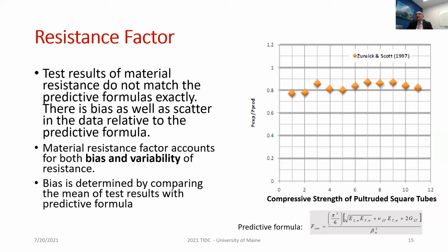What is bias? I present to you the compressive strength of pultruded square tubes, and you will see that using the best equation that money can buy, still the test results coalesce around 80% of the predicted value. Therefore, there is a bias of 0.8 that has to be accounted for.